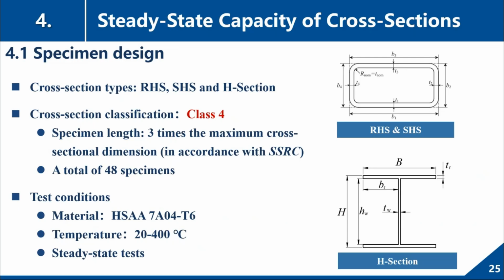Before the theoretical work, we also carried out a series of cross-section tests. So the tests include three kinds of cross-section types. They are RHS, SHS, and H section. All of them are in class 4, that is slender cross-section. And the material we employed was high-strength aluminum alloy, and the temperature ranged from 20 to 400 centigrade. And they are all steady-state tests.